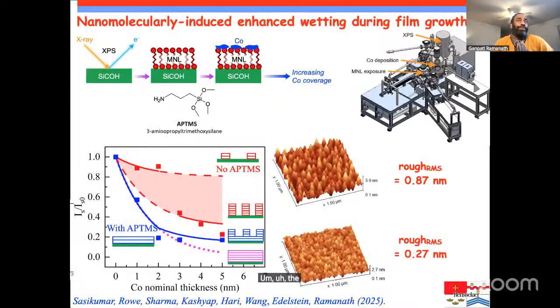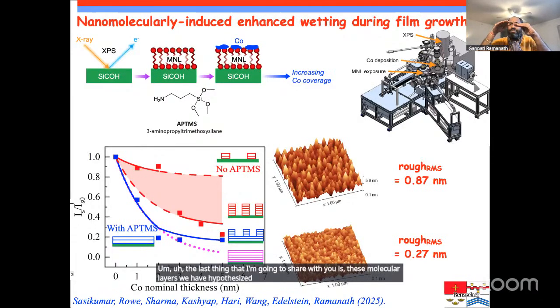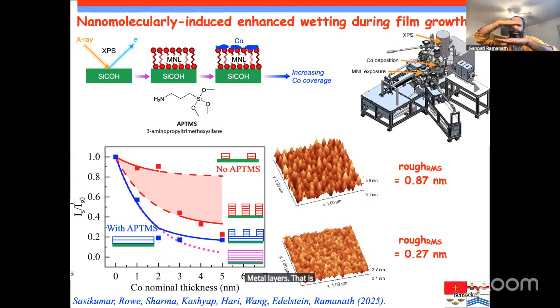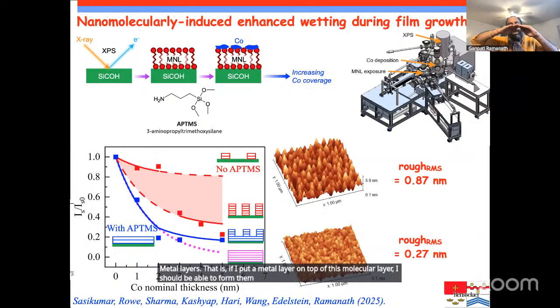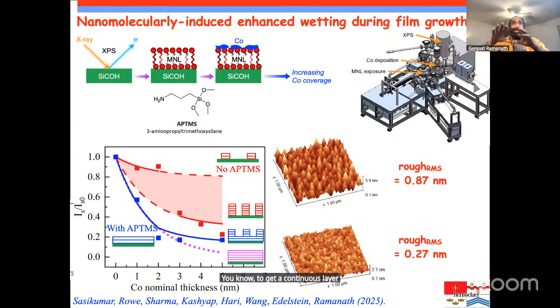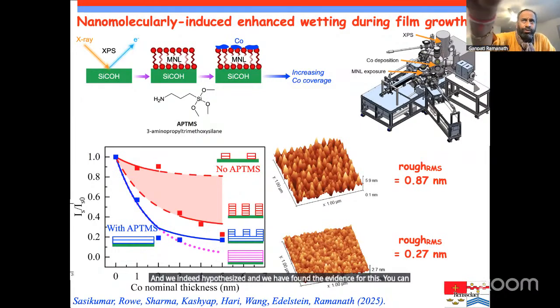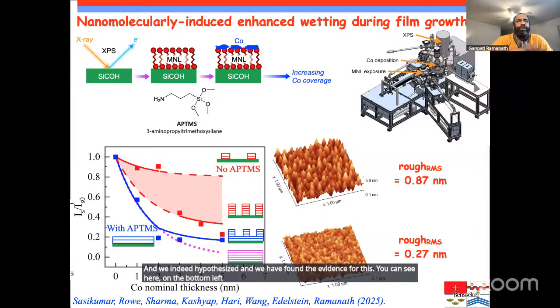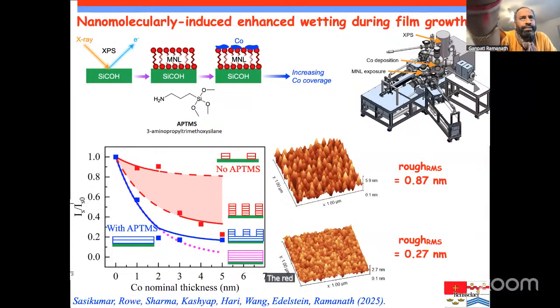The last thing that I'm going to share with you is these molecular layers we hypothesized can actually wet metal layers. That is, if I put a metal layer on top of this molecular layer, I should be able to form them much thinner, to get a continuous layer than if the molecular layers were not there. And we indeed hypothesized, and we have found the evidence for this. You can see here on the bottom left graph, the red data points basically follow islanding.